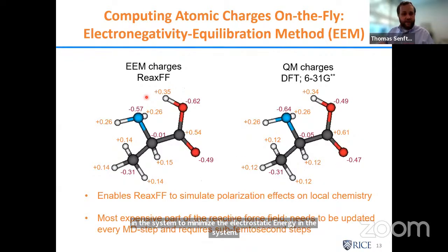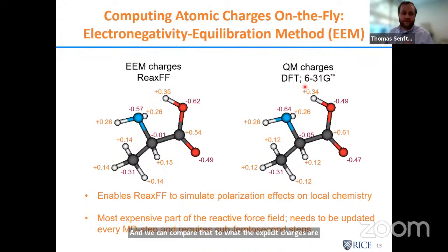And we can compare that to what the explicit charges are calculated at the DFT level or the quantum mechanical level. So this allows ReaxFF to describe polarizability, and it allows us to update the partial charges as bonds break and form. If a water molecule dissociates, right, it needs to dissociate into a proton and a hydroxide, not the two neutral radicals. And this charge equilibration scheme enforces that.